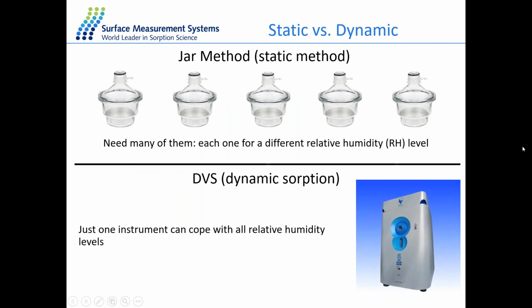Here is just a basic comparison between the static method and the dynamic vapor method. In the traditional method, which is known as the jar method, each jar here will represent one relative humidity. So you need to put the sample in the jar, wait for a very long time, and then take the sample out for the measurement. During this process, you will have the problem of contamination for the sample or the loss of the sample. So the result will not be as accurate as the dynamic vapor sorption.